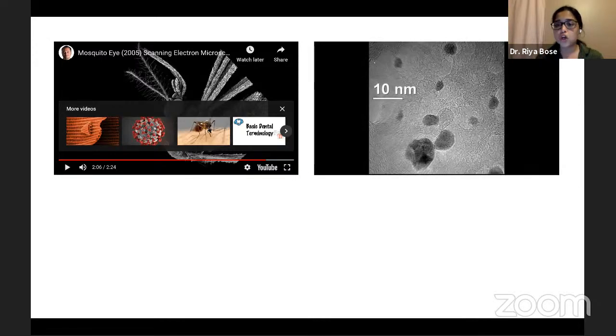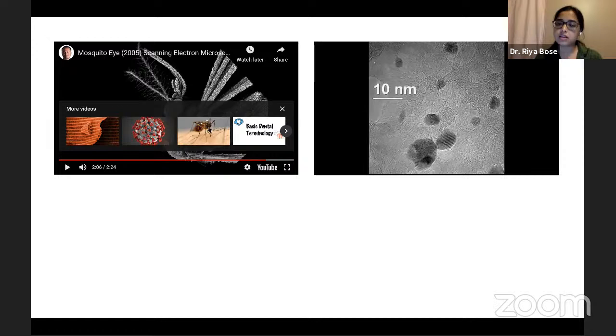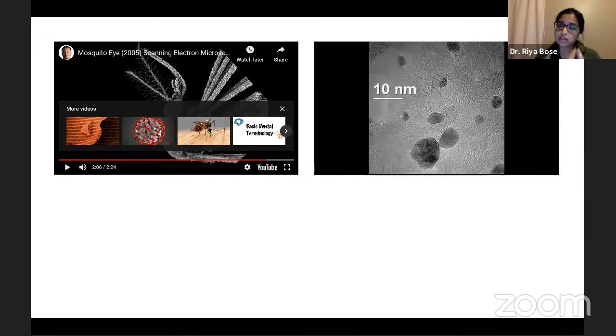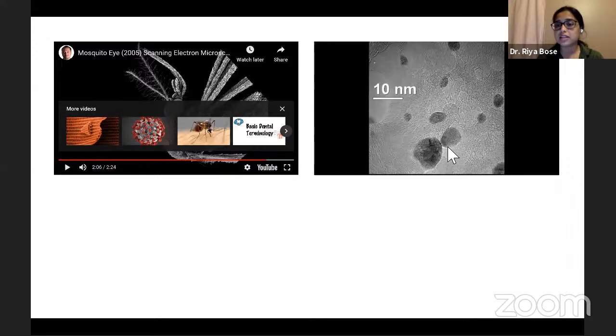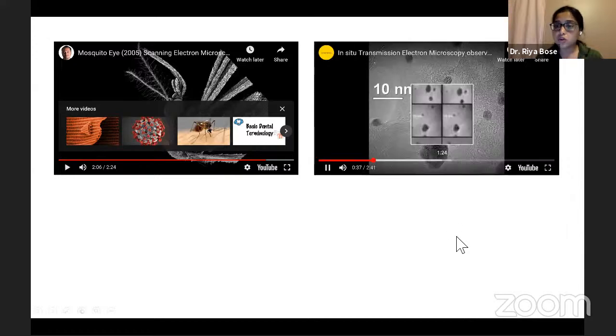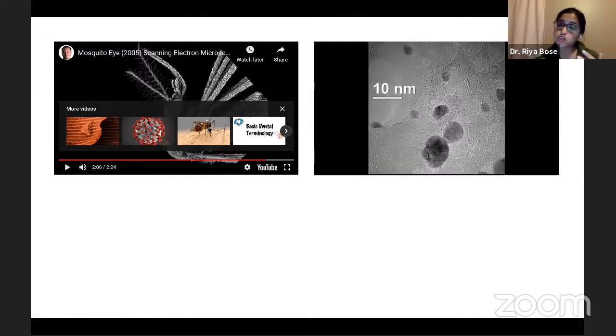So you can estimate the size of these particles, and even those reactions that are occurring in nanoscale with such small nanoparticles under TEM, you can directly see them. And now you can see that they have really come close and they are coalescing together. And not only can you see that they are coalescing together physically, if you zoom in, you can see how their lattice planes are transforming once they are coalescing together.